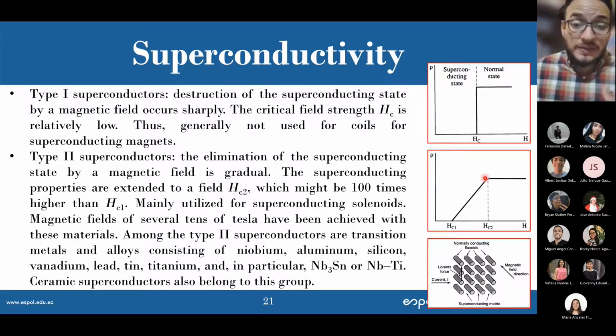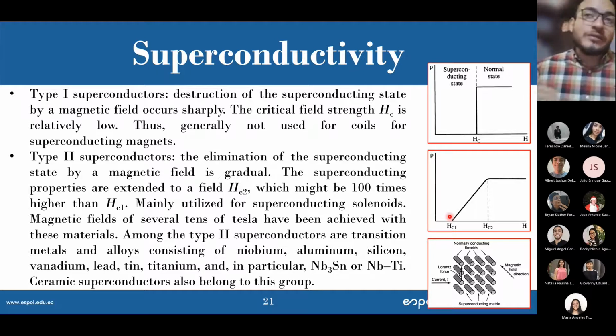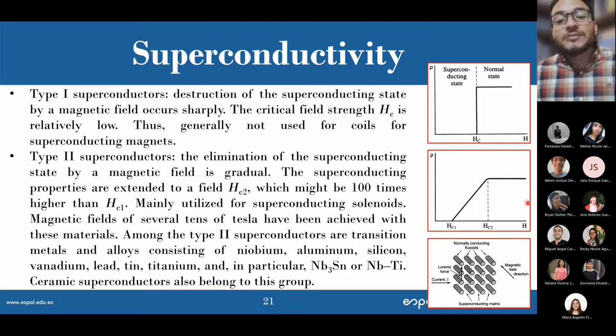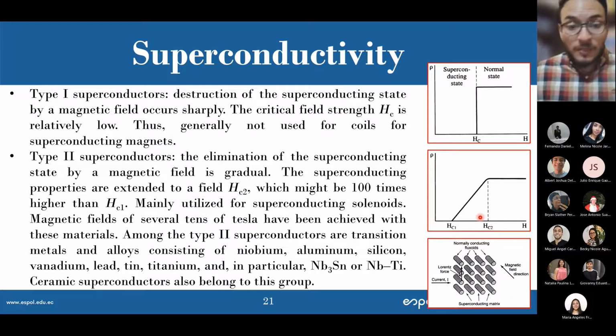This is a big advantage, because the difference between the second critical value and the first critical value can be 100 times, which is very useful, because that allows me a wider window of maintaining a superconducting state. Well, not a fully superconducting state, but at least I don't have the full resistivity that I do when I reach the normal state, after passing this second critical magnetic field strength. So these types of materials are the ones used for solenoids and coils in superconducting magnets, right?